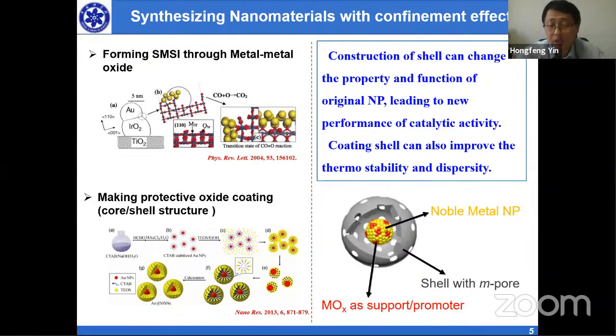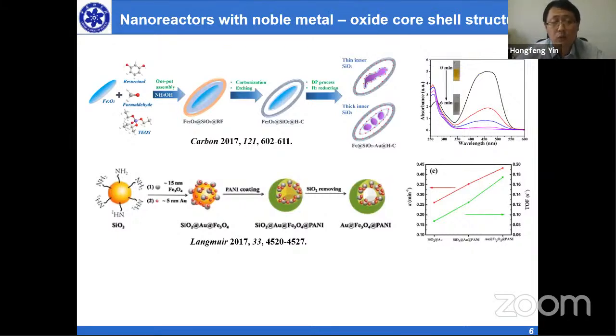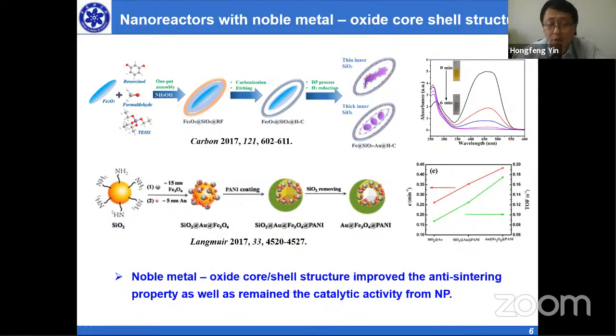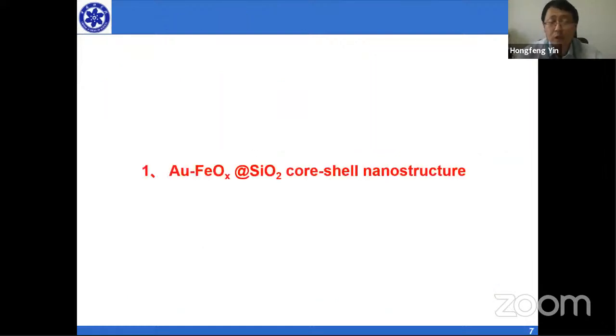So it will be a pretty good way to solve the aggregation problem as well as to have a good activity. There is much work that has been done this way. For example, silica with gold can have an interaction, as well as carbon as a shell. Another work, like gold having good interaction with iron oxide, and the shell can protect it from aggregation. So noble metal oxide core-shell structure can improve the anti-sintering property as well as keep the catalytic activity of the nanoparticle. That's the target. I'm going to talk about my work.